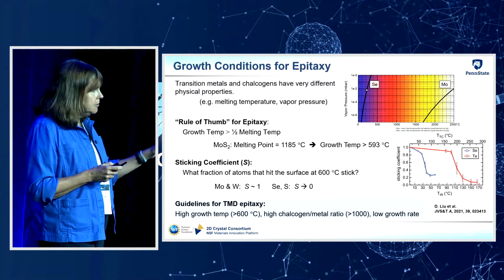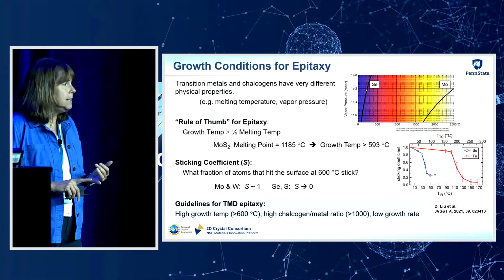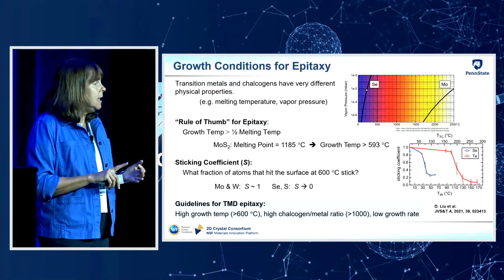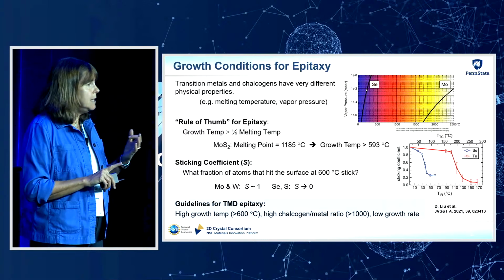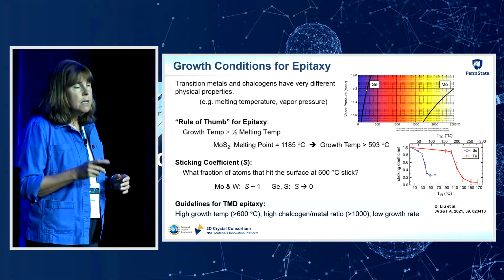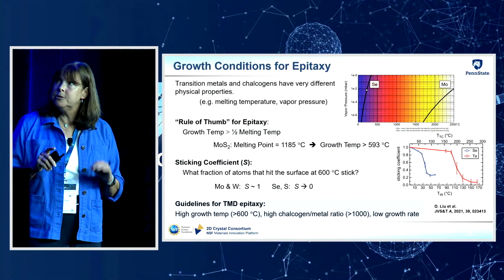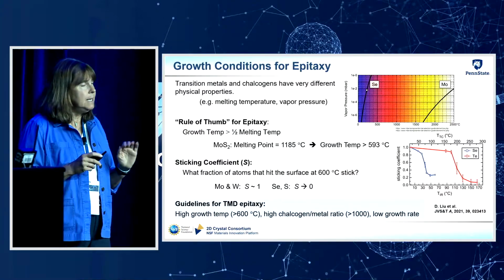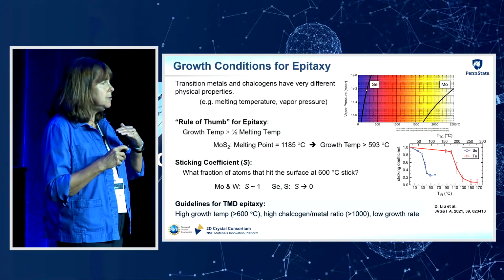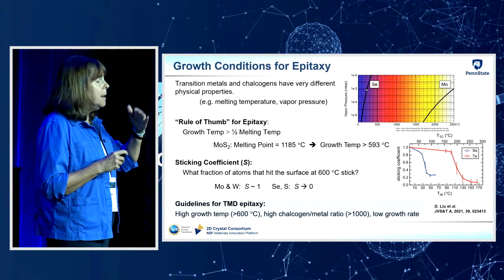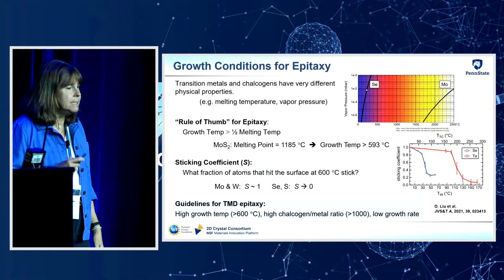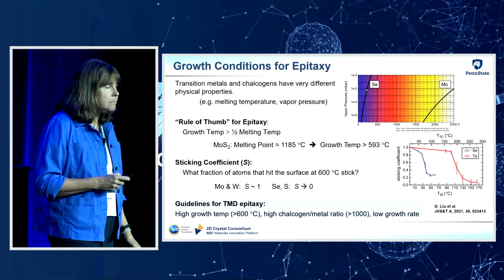In contrast, we have the chalcogens, things like selenium and sulfur. Those have low melting temperatures and high vapor pressures. So if you just compare the vapor pressure of selenium to molybdenum at a given temperature, you can see that there's orders of magnitude higher vapor pressure of something like selenium compared to molybdenum.